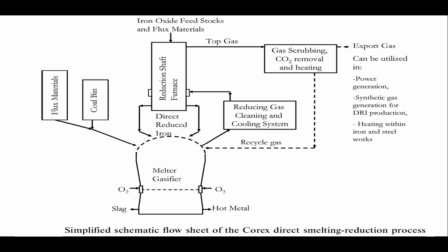This gas usually contains 85% carbon monoxide. The Corex reduction shaft furnace eliminates the softening and cohesive zone of the traditional blast furnace, thus resembling the shaft furnace utilized in Midrex and HYL natural gas-based direct reduction processes. By eliminating the coke requirement, maintaining gas flow at these zones is also eliminated. Unlike shaft furnaces in natural gas-based direct reduction processes, sticking of the iron oxide feedstock to the furnace walls is not a problem in the Corex reduction shaft furnace, because the reducing gas usually contains coal dust which serves as a lubricant. The product of the shaft furnace — direct reduced iron — usually reaches up to 93–95% metallization and contains from 2 to 5 weight percent of carbon.